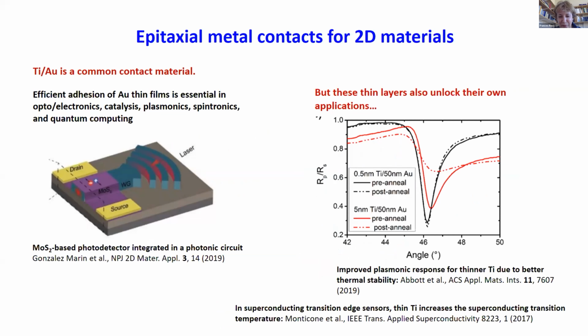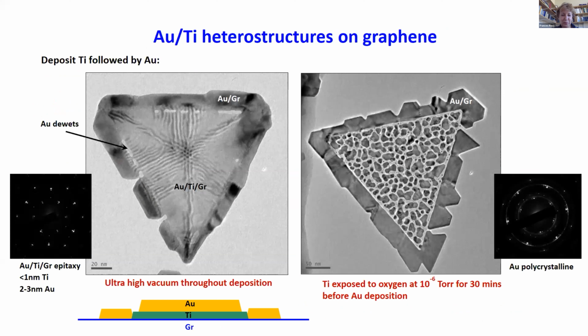And this would open up all kinds of opportunities if we could control the thickness and the size of the metal bilayer. And so this is what happens when we put Ti first onto graphene, and then we put gold on top. So in this first image, we put the Ti, we then put the gold, they align with each other in a very beautiful epitaxial way. You can see the moiré pattern, you can see a rim of gold around the outside, and you can see every crystal is aligned with each other here.